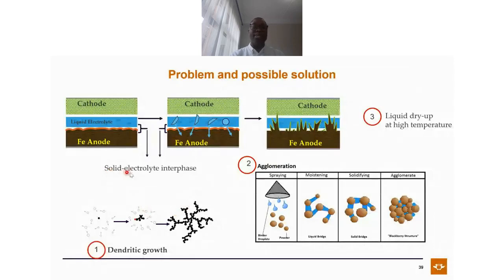This normally happens at the solid electrolyte interface. So we want to make it a solid electrolyte interface to avoid this. This is due to water. Another thing that happens is agglomeration. If you have water here, water-based material, and you have anode, and remember this is powder, the water is able to fuse all of this material and make it agglomerate. The moment it's agglomerated, we all know that it no longer functions the way it should. Also, this liquid dries up at a higher temperature. So these are the basic problems which are affecting the ion air batteries.